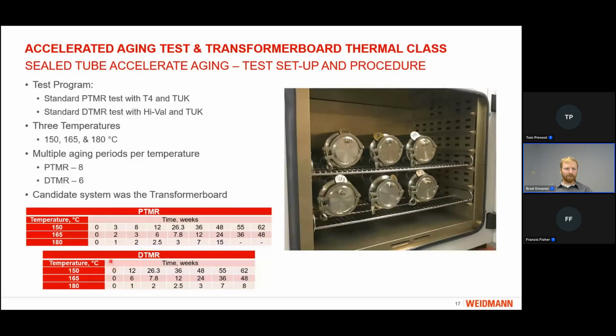At the highest temperature, a minimum of 1 week, but at the lowest temperature, you can see we went out to a maximum period of 62 weeks. Just showing that although these are accelerated tests, they still do take a significant amount of time. And we defined in this test series our candidate system to be the transformer board within those material ratios.